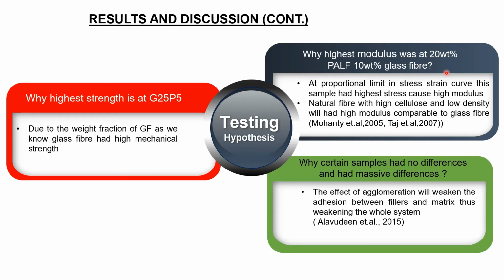Meanwhile, why was the highest modulus at 20% PALF, 10% glass fiber? It is because of the proportional limit in the stress-strain curve; this sample had higher stress, causing high modulus. Other than that, natural fiber with high cellulose and low density will have high modulus comparable to glass fiber. Last one, why did certain samples have no differences and others massive differences? The effect of agglomeration will weaken the adhesion between fillers and matrix, thus weakening the whole system.